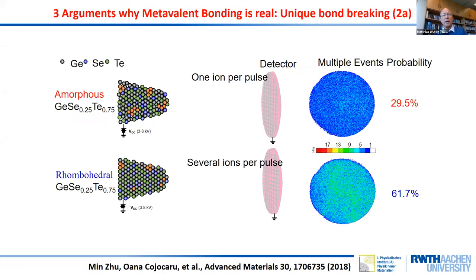We can do something else. We had an interesting experiment performed on two different modifications of a phase change material. This is a compound of selenium, tellurium, and germanium in the amorphous state and the crystalline state. We make a very sharp tip of this material and put this into an atom probe where we now dislodge atoms upon the application of a short laser pulse. And typically for the amorphous material, for a successful pulse, we typically only create one fragment. During the same experiment, for this crystalline state here, typically we dislodge several fragments. So the bond breaking differs.